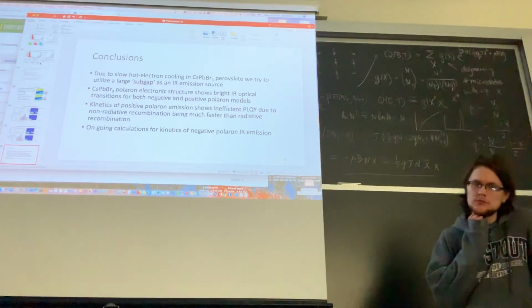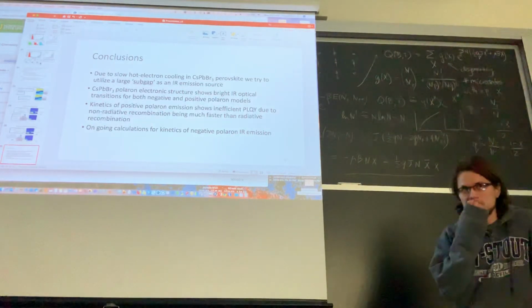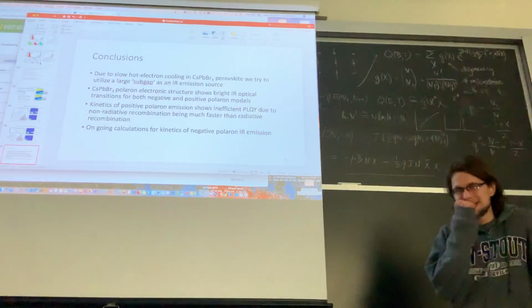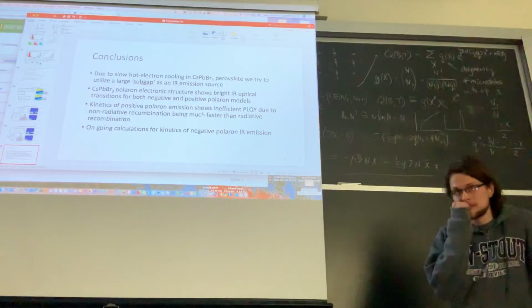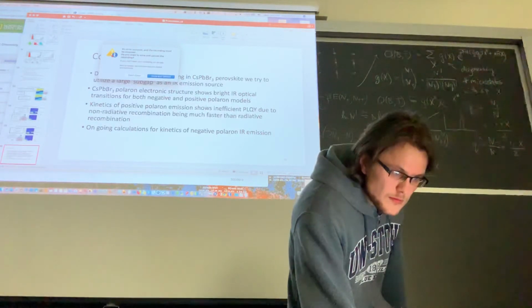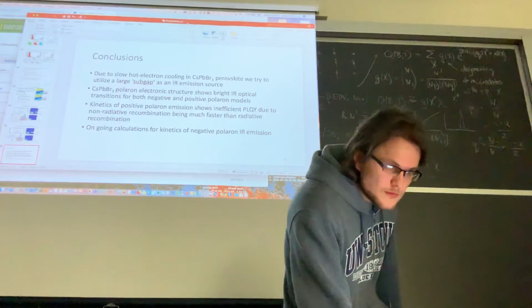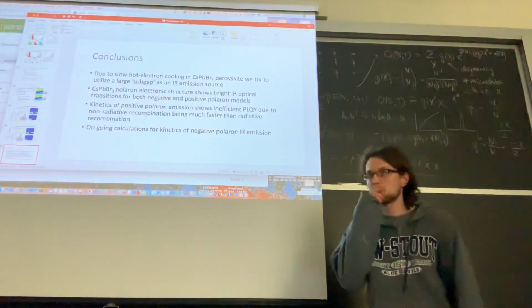If the system is charged, if either positive or negative charge is injected, then it will be recombination of particle and hole, but their energy offset will be much less. For a positive polaron, the particle will be on top of the valence band, and the hole will be the next state on top of the valence band.